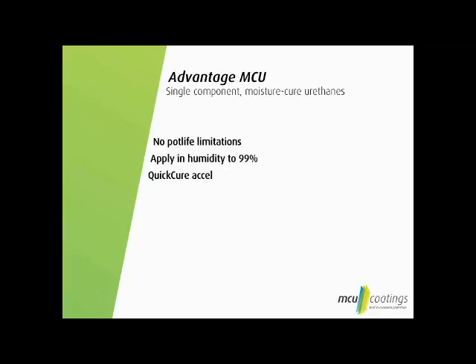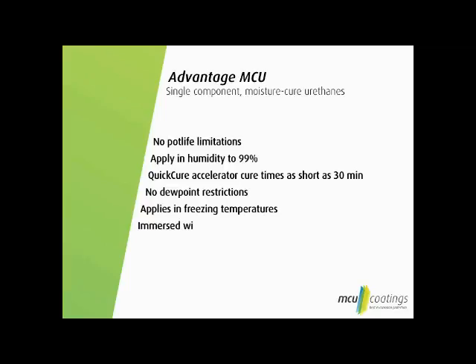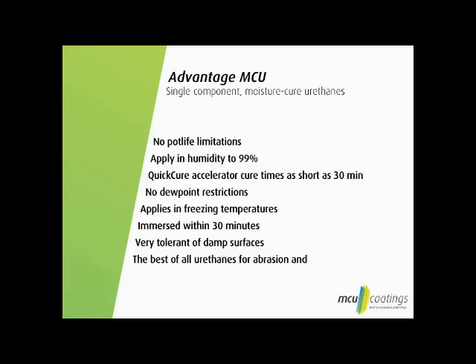Advantage MCU. MCU Coatings manufactures moisture-cure urethanes and is dedicated to this technology. As you will see, these coatings solve all the application problems found in two-part epoxy, urethane, and inorganic coatings and still give far better corrosion resistance. Take a look at MCU Coatings' single-component moisture-cure urethanes compared to plural-component coatings. MCU urethanes have no pot life limitations, require no catalyzation or mixing. Two-component urethanes and epoxies have short pot life and must be pre-blended.